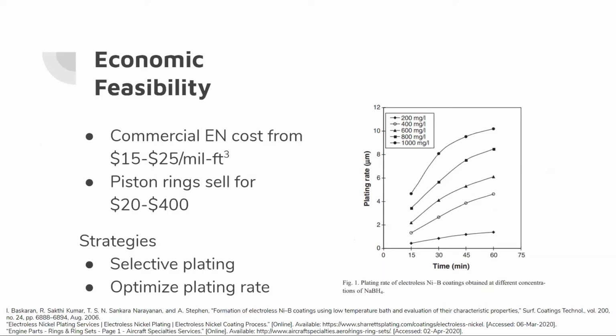The first is selectively plating only the surfaces with high contact with the piston. This includes the groove and the ring side. By looking at only these two surfaces and plating them with this composite, we are able to optimize the plating, reduce the material used, while making sure that the performance of the ring is maintained.